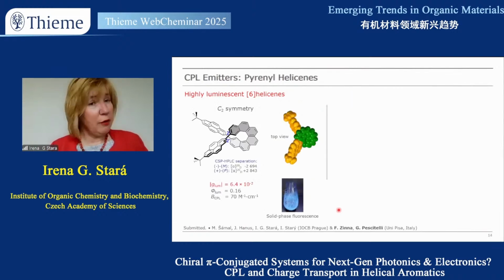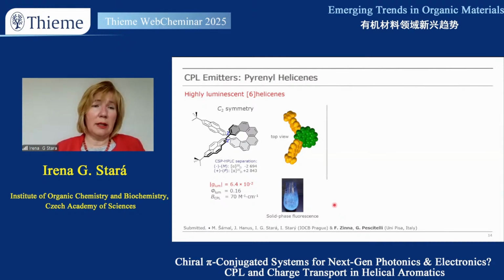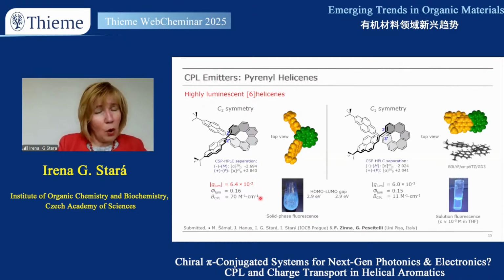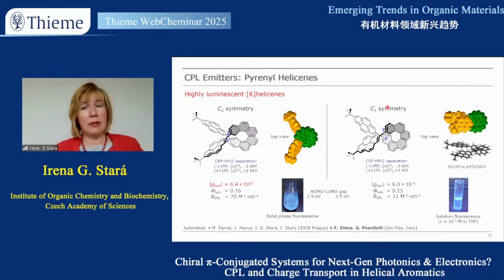We also investigated CPL emission of this C2 symmetric compound. We found that even though this structure has no chance to create an intramolecular excimer, g_lum still remains very high. Brightness is a bit lower. Then we also made a C1 symmetric compound, as you can see in this picture. Here the pyrene units are nicely oriented to be in close proximity. But for this C1 symmetric compound, you can see a dramatic decrease of g_lum, from 10 to the minus 2 to 10 to the minus 3, and the brightness is also much lower.